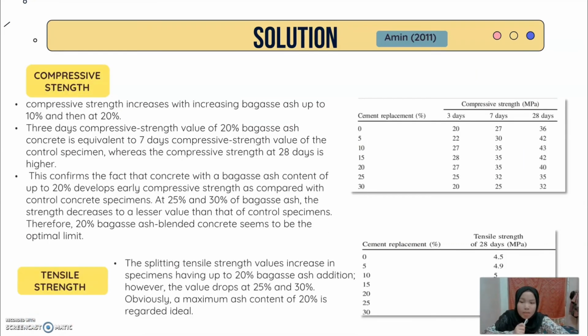For Amin, the compressive strength increased with the increasing bagasse ash up to 10% and then at 20%. For tensile strength, splitting tensile strength values increase in specimens having up to 20% bagasse ash addition. However, the value drops at 25% and 30%. Obviously, a maximum ash content of 20% is regarded as ideal.